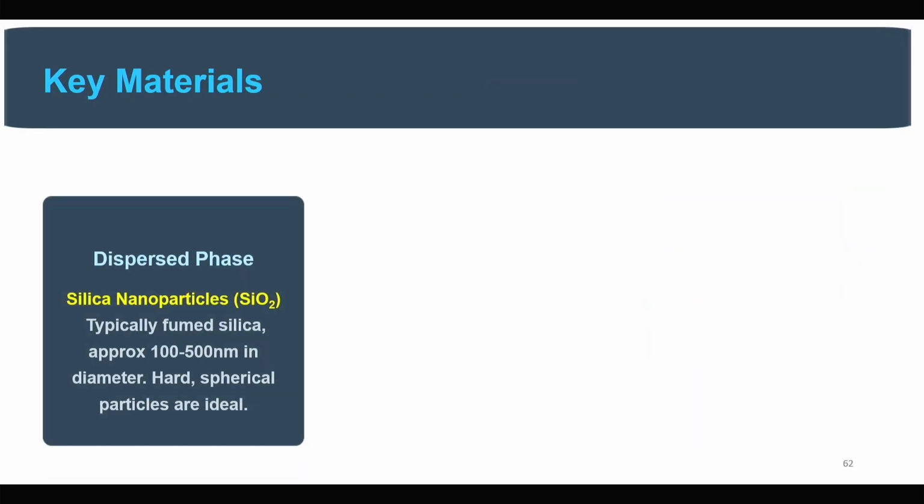So, the main materials are silica nanoparticles, typically fumed silica, approximately 100 to 500 nanometers in diameter. These are hard spherical particles.